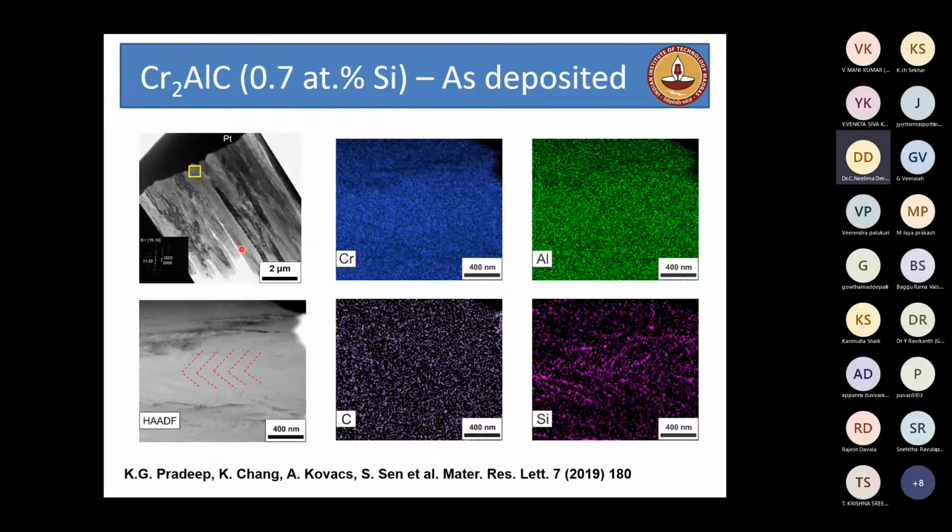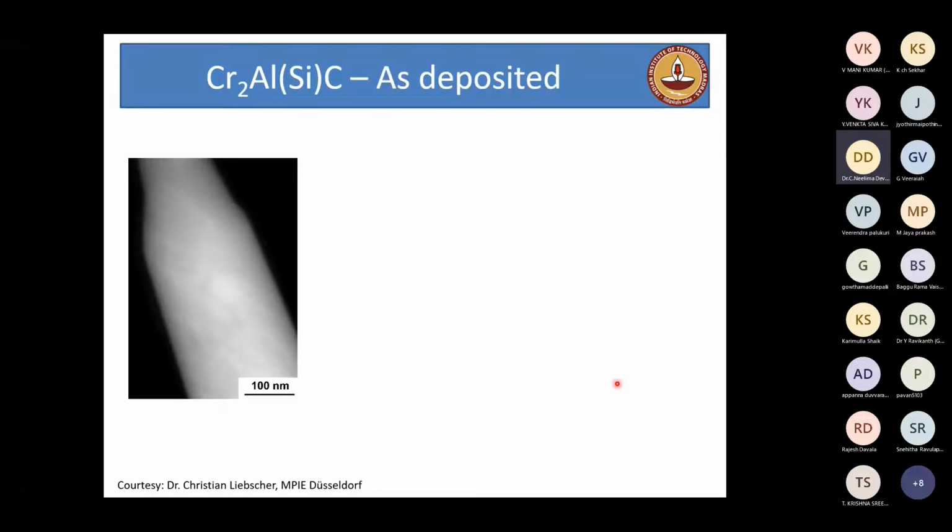So now you try to see them in 3 dimensions because there is nothing much you can do beyond this limit of STEM EDS. So you take this into atom probe, you prepare the sample in the form of a needle, then you can see in a HAADF image that there is a lighter contrast visible at periodic locations, which resembles the V-shaped morphology as you've seen before.